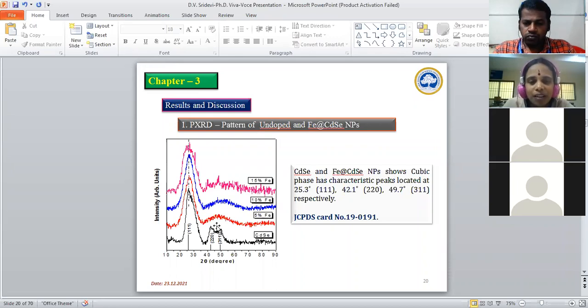If so, is there any change in structure or the lattice value? No, sir. But it is confirmed in SAED patterns, sir. The rings are not obtained when Fe is doped into the cadmium selenide nanoparticles. For pure cadmium selenide, sharp rings were observed, but in Fe doped cadmium selenide nanoparticles, the second and third rings are not shown clearly, sir. Have you calculated the lattice value for the pure and iron doped one? Yes, sir. Then only we can come to the conclusion.